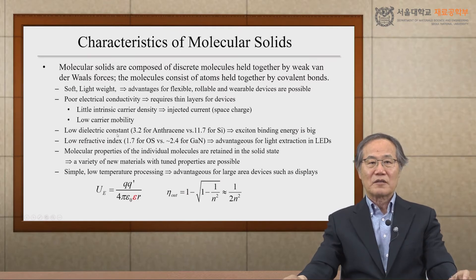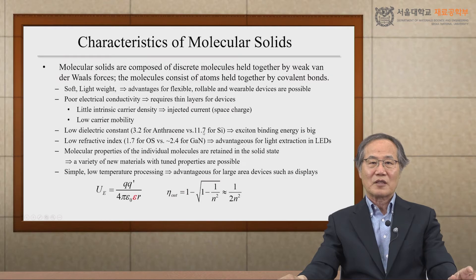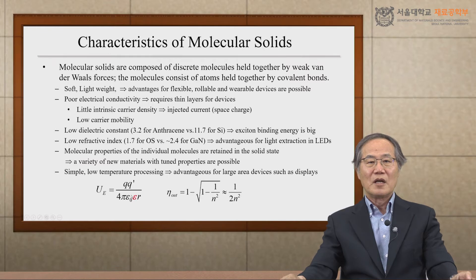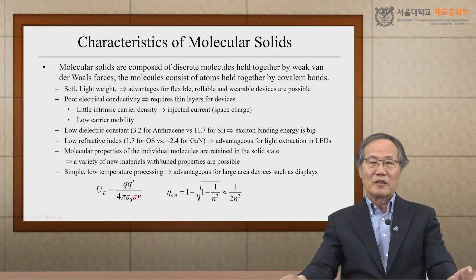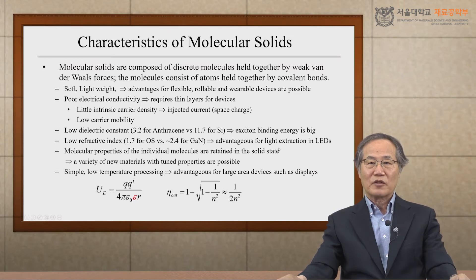Organic semiconductors also have a low dielectric constant — about 3.2 for anthracene versus 11.7 for silicon. The implication of a low dielectric constant is quite significant. For instance, exciton binding energy is much larger in organic semiconductors compared to inorganic semiconductors. Looking at the binding energy of positive and negative charges, you can see that epsilon appears in the denominator, meaning the binding energy in organic semiconductors is about four times larger than in silicon. That implies major differences in light emission processes. Also, the refractive index is small, which is advantageous for light extraction compared to inorganic LEDs.